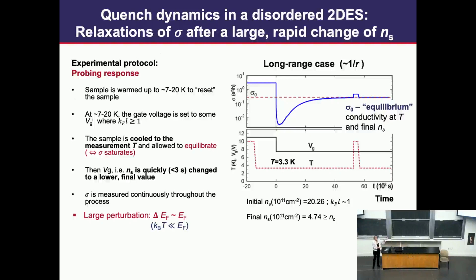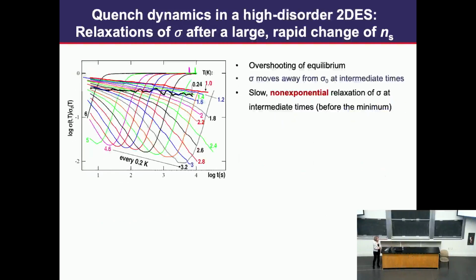You can repeat this measurement at different temperatures and get a bunch of curves shown here. We're plotting this conductivity normalized by the equilibrium conductivity for each temperature. In other words, on this log scale, zero is the equilibrium conductivity for each of these curves.